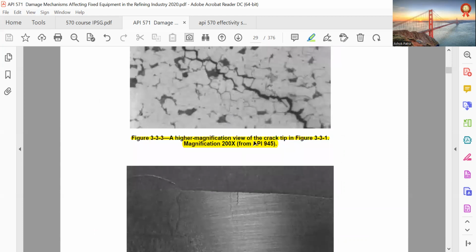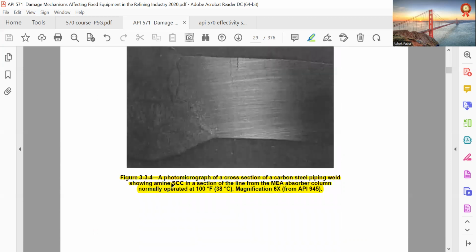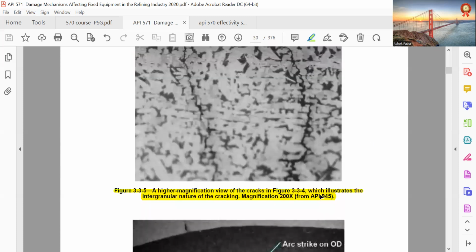These are higher magnification views of the crack tip in figure 3.3.1, magnification 200x, from API 945. Then a photomicrograph of a cross section of a carbon steel piping weld showing amine SCC in a section of line from the MEA absorber column, normally operated at 100 degrees Fahrenheit, 38 degrees centigrade, magnification 6x from API 945. A higher magnification view of the cracks in figure 3.3.4 illustrates the intergranular nature of the cracking, magnification 200x.